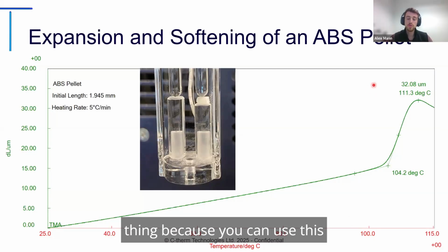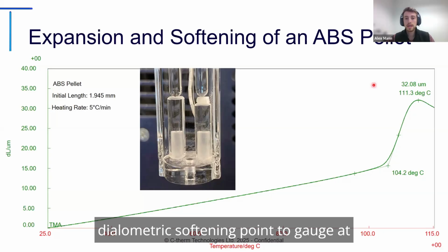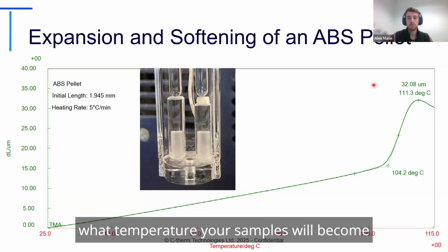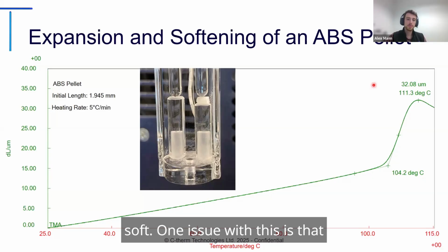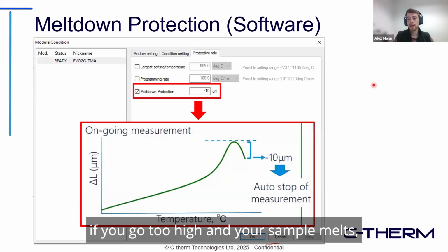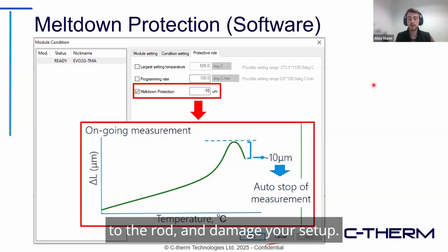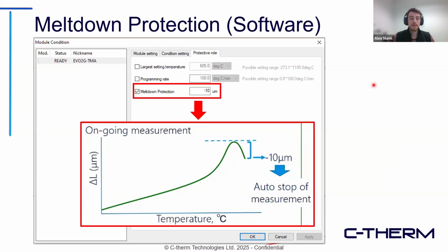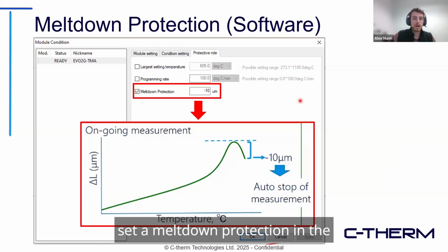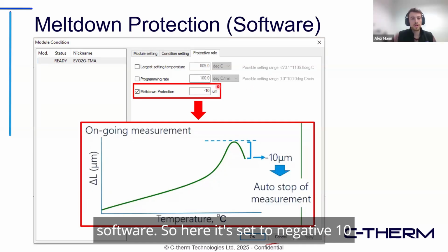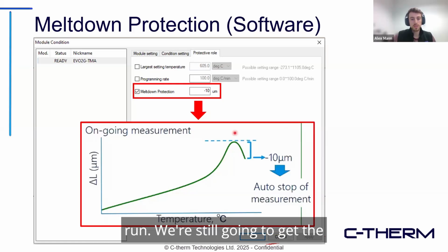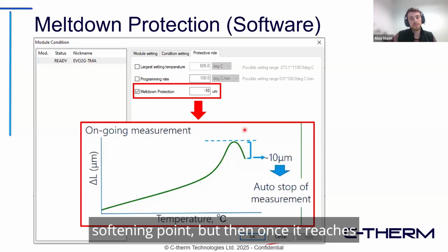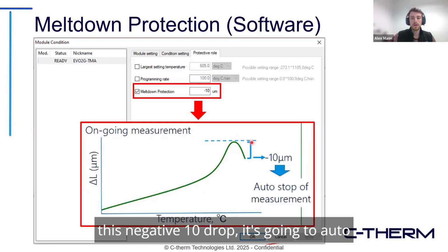And that's not a bad thing because you can use this dilatometric softening point to gauge at what temperature your samples will become soft. One issue with this is that if you go too high and your sample melts, or if you enter the sample too much, it can fuse to the support tube, it can fuse to the rod and damage your setup. So essentially what you can do is set a meltdown protection in the software. Here it's set to -10 microns. So we're going to measure our run. We're still going to get the softening point, but then once it reaches this -10 drop, it's going to auto stop the measurement.